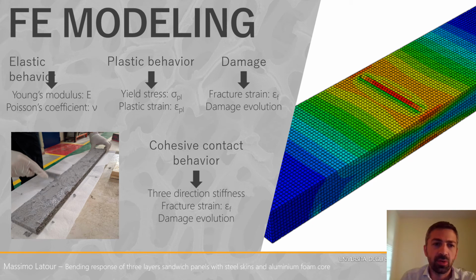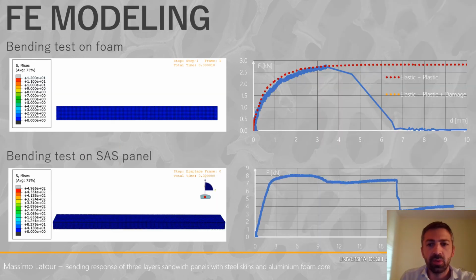Finite element models were also developed during the work. In particular, we have developed a finite element model through Abaqus, modeling the materials with elastic plastic behavior, considering the damage initiation criteria and the damage evolution law. The glue was modeled with a cohesive contact behavior. This cohesive contact, for its definition, needs the definition of stiffness in the three directions, and the definition of fracture strain and damage evolution, which governs the debonding of the steel skins over the aluminum foam. Also, the model was providing a very accurate representation of the experimental behavior.